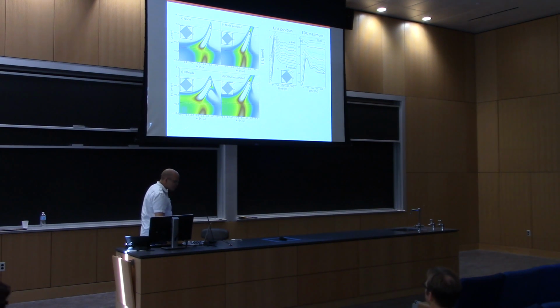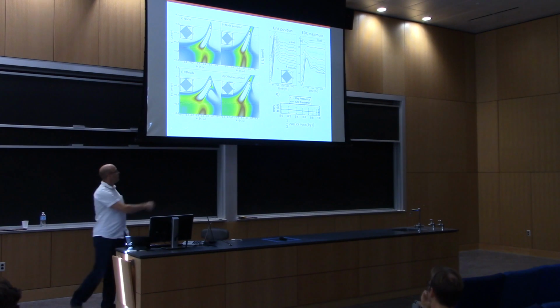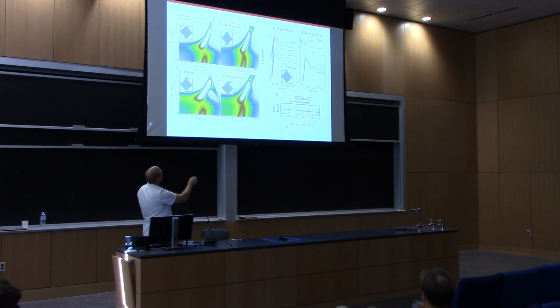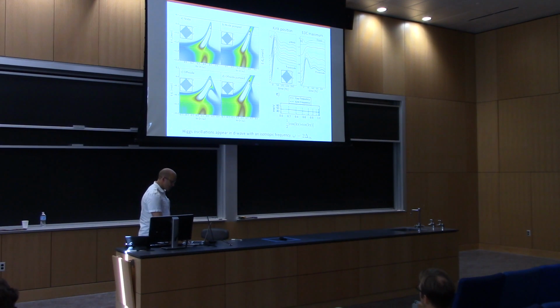And the point is that these oscillations are isotropic in frequency. Doesn't matter where you sit along the Fermi surface, I see the same frequency. That being of the antinodal gap. In particular, it being the antinodal gap after I've pumped the system. In other words, how much superconductivity is left, those are the oscillations we're going to see.